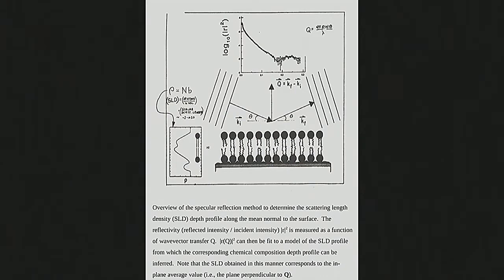Here's another slide that reinforces that idea. If we measure as a function of angles — starting at smaller angles, going higher, maintaining the specular condition — the reflectivity as a function of the wave vector transfer Q, which is proportional to the angle since Q = 4π/λ × sin(θ), gives us the depth profile. You can see where the head groups of this lipid bilayer system are, what's in between, and so on.